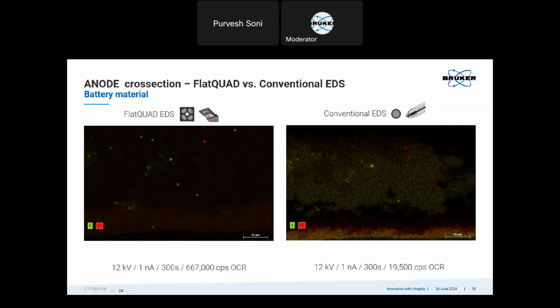And because of the high signal to noise ratio and also the 4-segment design, I could see particles which were there, but the data was not there because of the inclined detector geometry. So here you can see these two particles. They can be seen with the FlatQuAD, but with a conventional detector, we cannot see them. And here you can also see that the difference between the noise, which is in this region, and the signal is almost the same. So that's why you see more noise, but the signal to noise ratio is very good for the FlatQuAD, and that's why we could see these particles very nicely.